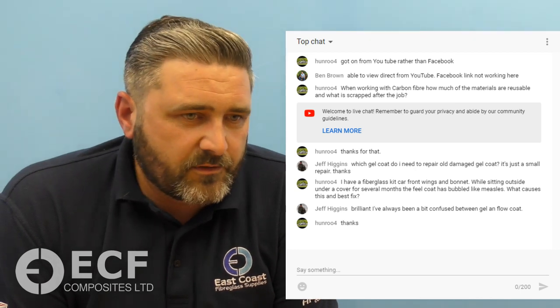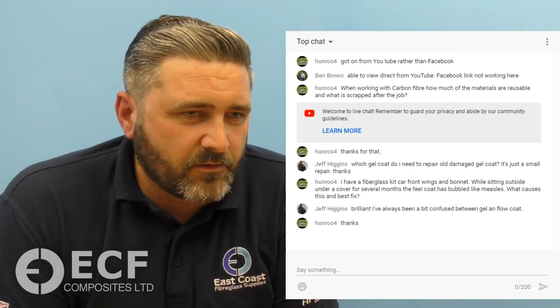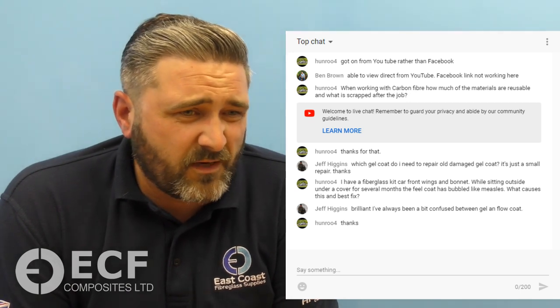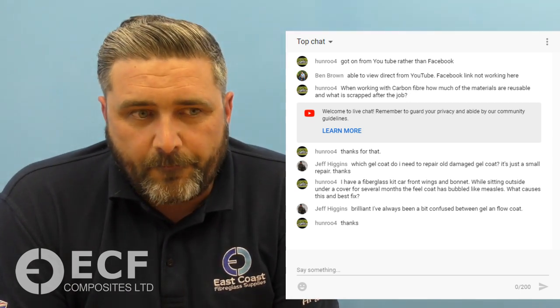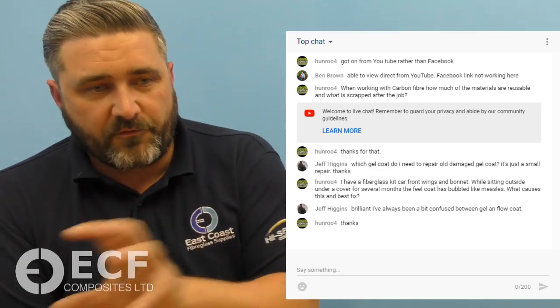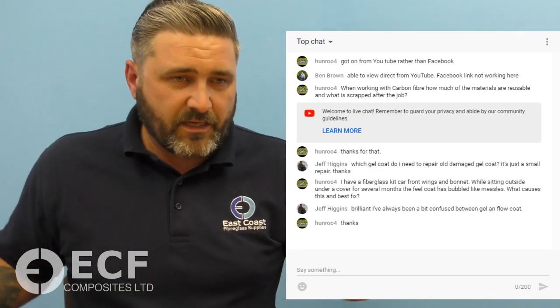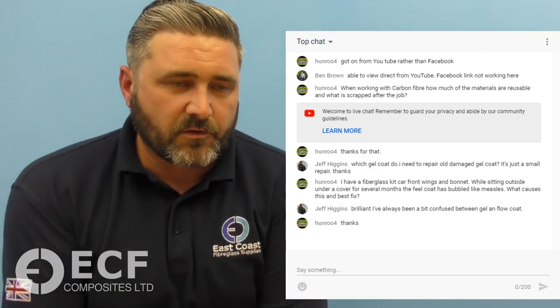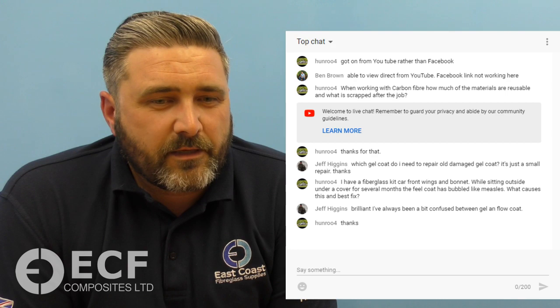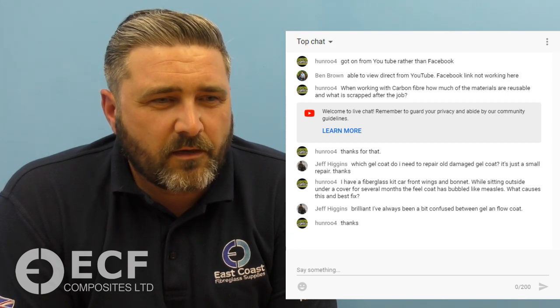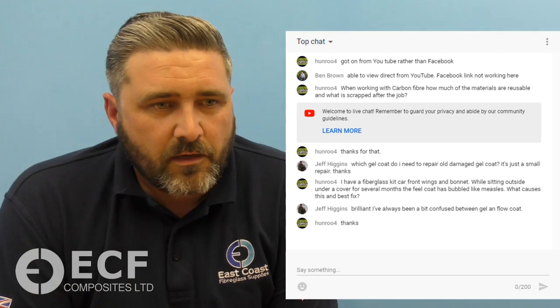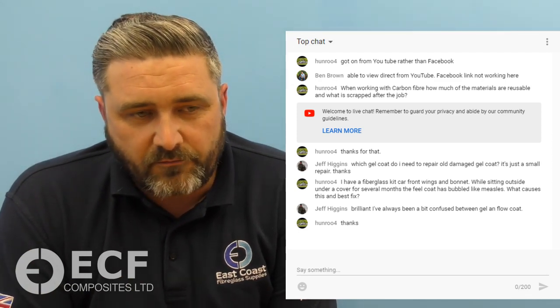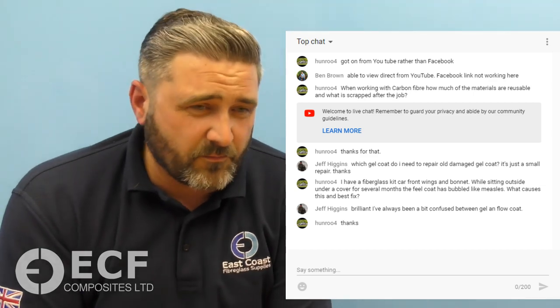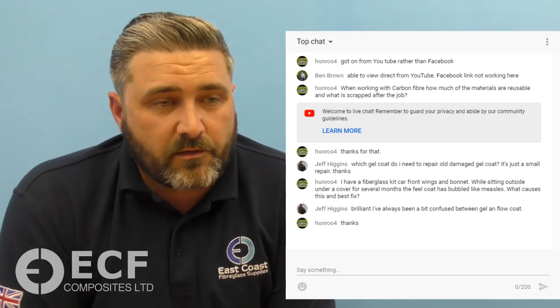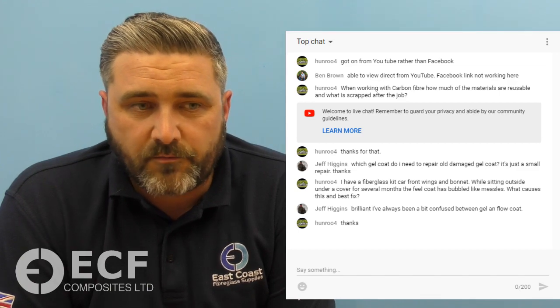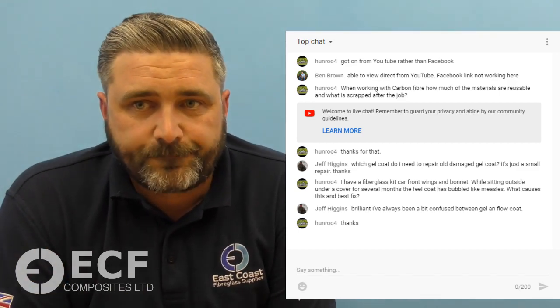Usual recommended temperatures around about 18 to 20-25 degrees, something around about that. And always condition your product to temperature before you use it. It's no good having a nice room temperature and then starting to use a cold product. And usual catalyst dosage is about 2%. You can increase it to compensate for the cold, but whenever you're doing anything that's in the wrong kind of temperatures, that differs from the data sheet, you are running the risk of things going wrong that way. So always consult the data sheet before you use the product.